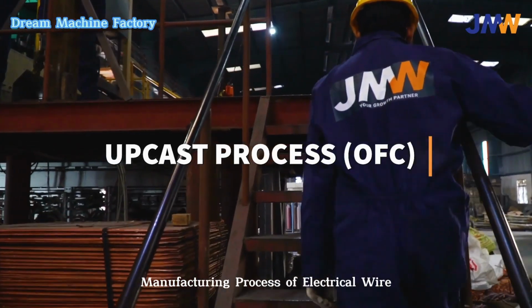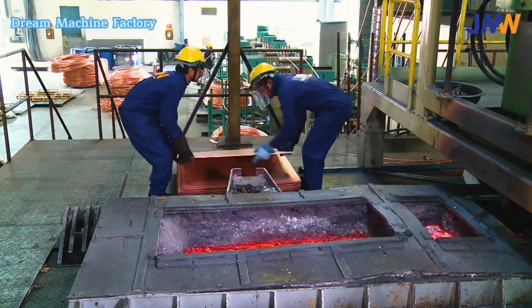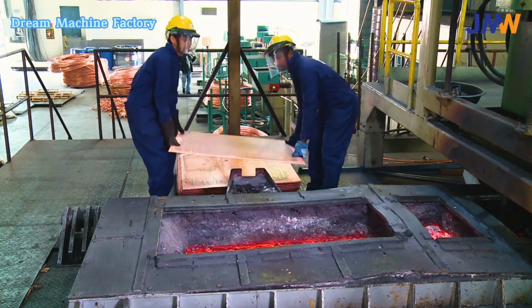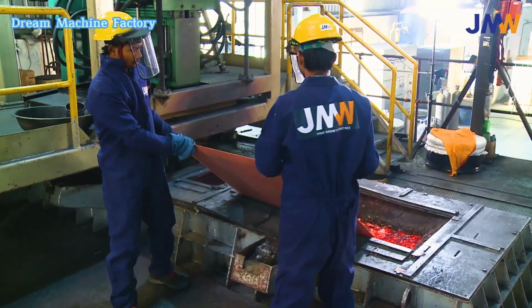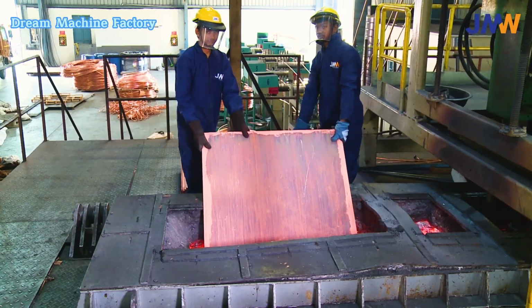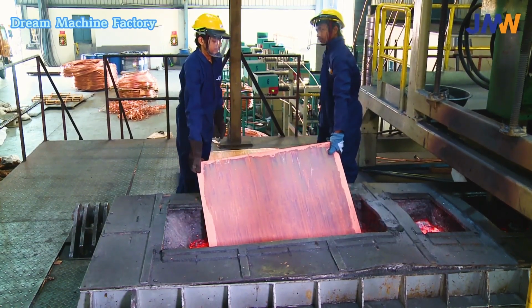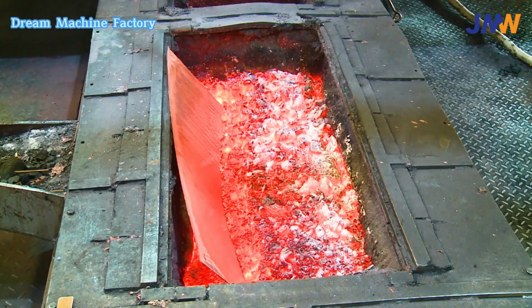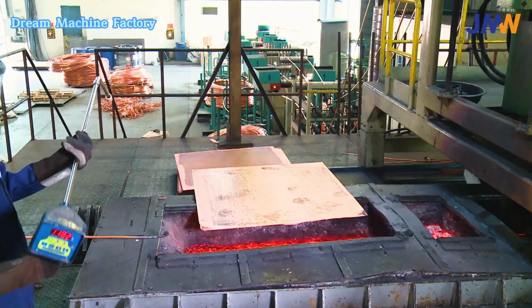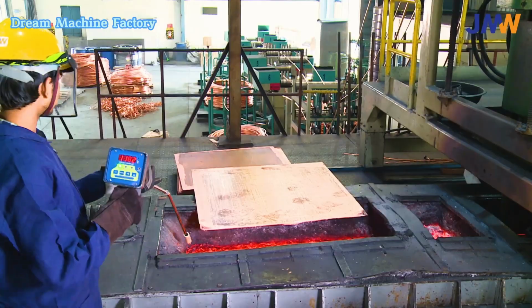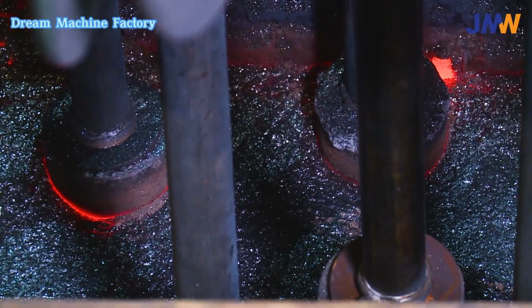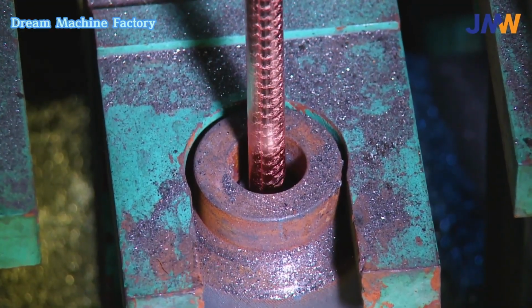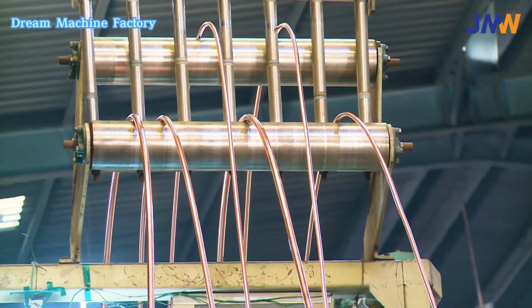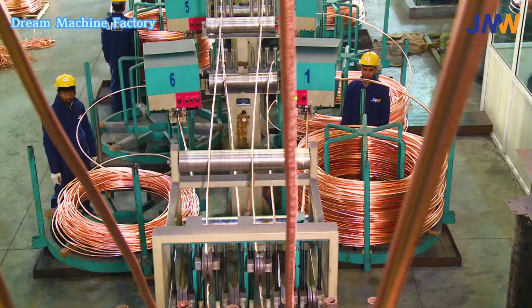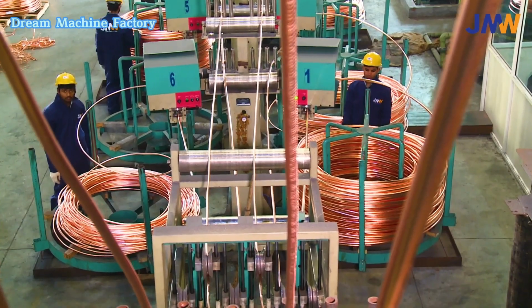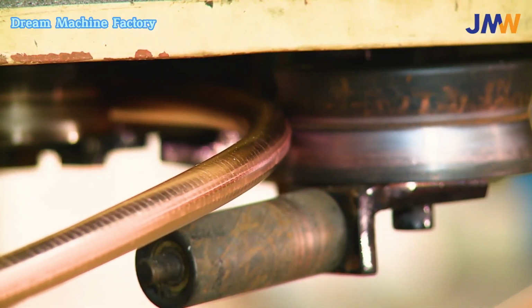The upcast process is a vertical continuous casting method used to produce oxygen-free copper, OFC rods, known for their exceptional electrical conductivity and purity. In this process, high-purity copper cathodes are melted in an induction furnace under a protective atmosphere to prevent oxidation. The molten copper is then cast upward through graphite molds, which are water-cooled to solidify the metal into rods as it rises. The rods are typically produced in diameters ranging from 8 mm to 30 mm, depending on the application.